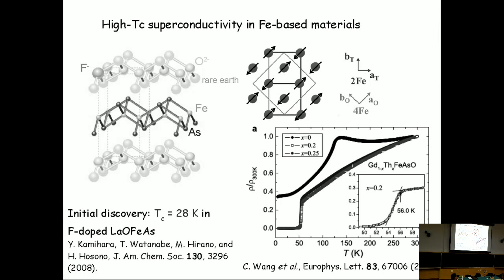So for the undoped compound, we have this magnetic structure, and if you measure resistivity, you get something like this black curve here. You have a peak or a maximum in the resistivity at a temperature nearby 140 Kelvin, and below this temperature the resistivity drops, and this temperature corresponds to the magnetic ordering temperature of these iron layers. And for the undoped compound, for this family at least, there is no superconductivity, while for the thorium doped, what happens is that this maximum temperature of resistivity corresponding to the magnetic ordering goes down in temperature, and finally disappears as the superconductivity shows up in these materials. So this is pretty much what happens. You have doping, you reduce the magnetic ordering temperature, and at some temperature the superconductivity comes up.